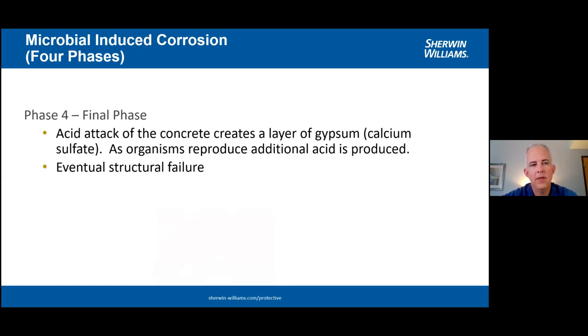And phase four, the final phase of this, the acid attack of the concrete creates a layer of gypsum. As organisms reproduce, additional acid is produced. And then we have eventual structural failure. Once this process starts, which is a naturally occurring process, it gets more aggressive and more aggressive and more aggressive. And that's how we end up with catastrophic failures.